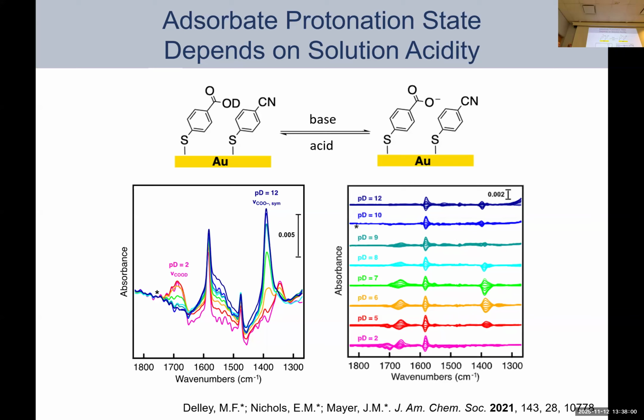Okay, and then as you increase the PD, so make it more basic, this large sort of broad feature eventually decays, and we see a large increase in this 1400 wave number feature. Okay, and so based on this and some literature precedent, we're able to assign the feature around 1700 to the carbonyl stretch of the protonated species, and this large feature around 1400 to the symmetric stretch of the carboxylate. Okay, these are just showing you that you can collect some really beautiful PD-dependent spectra, and now ATR-SEIRAS spectra.